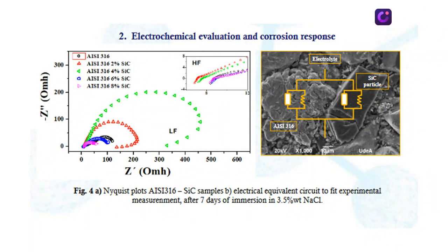For the electrochemical results, the impedance curves indicate that the 4% silicon carbide sample, after 7 days of immersion in sodium chloride electrolyte at 3.5% by weight, presents the highest capacitive arc, starting its decrease at 300 ohms, which indicates a higher resistance to permeation of the electrolyte through the microstructure of the material.